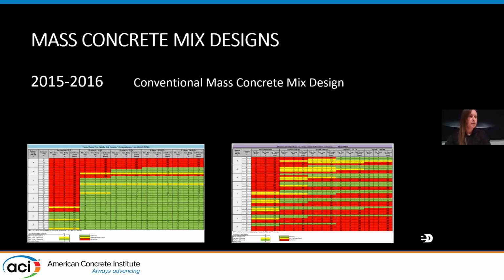We spent about a year between 2015 and 2016 pushing the specifications to allow for a higher percent supplementary cementitious material in the mix. Originally, it was dictated by the specs to have 49% slag replacement maximum, but after many meetings and durability trials, we were able to increase this limitation to 70%. We worked with 3 concrete suppliers on the project to test and develop a conventional mass concrete mix that would give us the most latitude to pour in various conditions. Then we ended up providing the teams with a thermal control plan similar to these tables, to visually display the various conditions and what maximum temperatures and differentials they can expect. This is for a conventional mix.